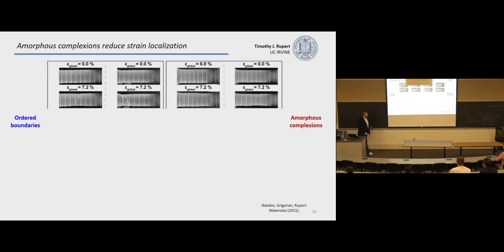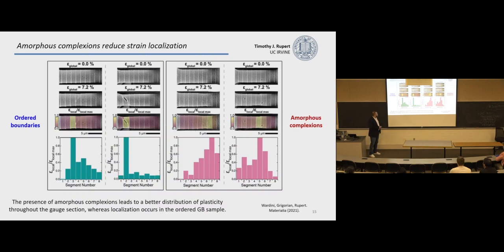With these little in situ experiments, we can also do fun things like look at how plastic strain is distributed in the gauge section. In this case, we put little platinum markers on the surface, and then we could track how the individual regions are elongating. And here we have a comparison of 4 different samples, 2 with ordered boundaries, 2 with amorphous boundaries. Here is a color plot, and here is the quantitative data.